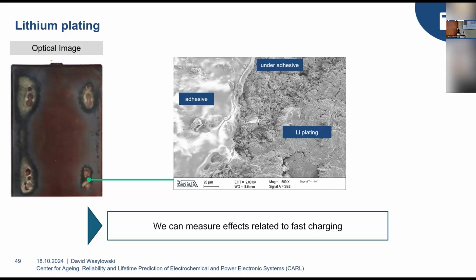So if we are in fact trying to help somebody parameterize its fast charging process, we only generate one image every 30 to 40 minutes, you can imagine that the fast charging process will be over by the time we have generated our first image. So this is not really helpful. And we actually solved this second issue by just using faster scanners, faster motors. You can see them in the first row.